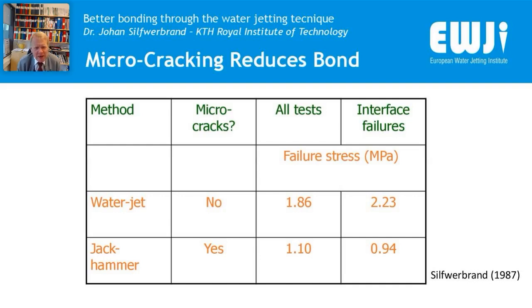bond strength. Sometimes 1 megapascal can be sufficient, but in a lot of circumstances we want to be closer to 2. And observe this was in the lab. In reality, we rarely reach the same values. So then it is very good to have a lab value which is about 2 megapascal, because then we can be certain that we will receive at least 1 megapascal in reality.